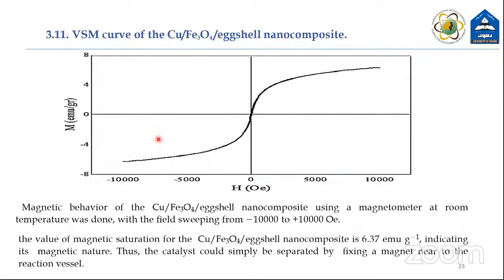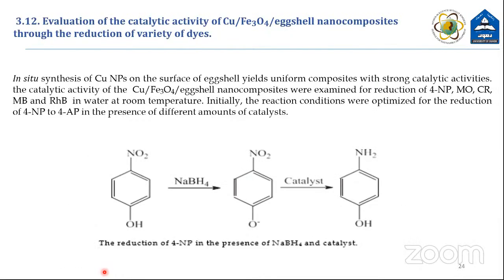VSM, vibrating sample magnetometer of the nanocomposite, indicates that the value of magnetic saturation here is about 6.37 emu, indicating that this nanocomposite has a magnetic nature, and thus the catalyst could be simply separated by fixing a magnet near to the reaction vessel.